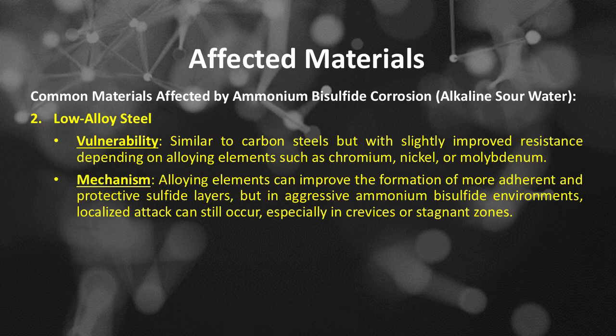Common materials affected by ammonium bisulfide corrosion or alkaline sour water, number 2, is low alloy steels. The vulnerability of low alloy steels: similar to carbon steels but with slightly improved resistance depending on alloying elements such as chromium, nickel, or molybdenum. The mechanism: alloying elements can improve the formation of more adherent and protective sulfide layers. But in aggressive ammonium bisulfide environments, localized attack can still occur, especially in crevices or stagnant zones.